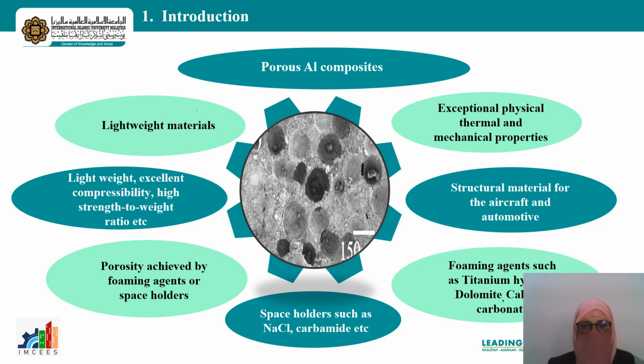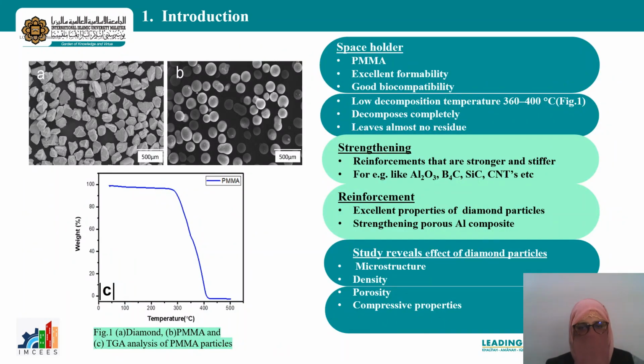But there are some problems associated with these foaming agents and space holders. The decomposition of the foaming agents leaves some residue behind. This can deteriorate the properties of the composites. Also, at times there is incomplete leaching of these space holders. To prevent all this, we are going to use polymethyl methacrylate as space holder particles, which have excellent formability, good biocompatibility, and a low decomposition temperature ranging from 360 to 400 degrees centigrade, and decompose completely, leaving no residue behind.